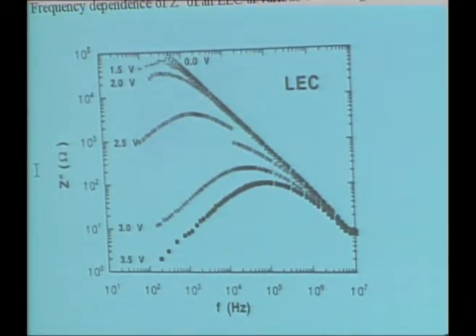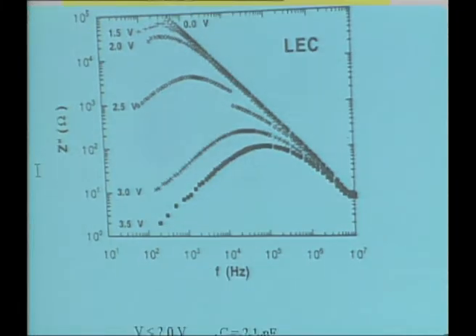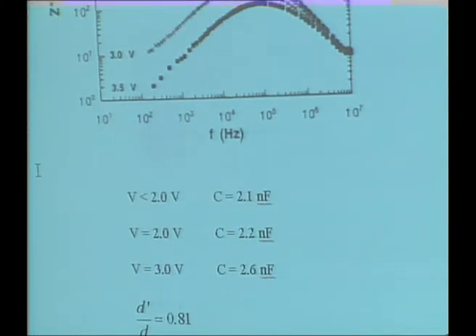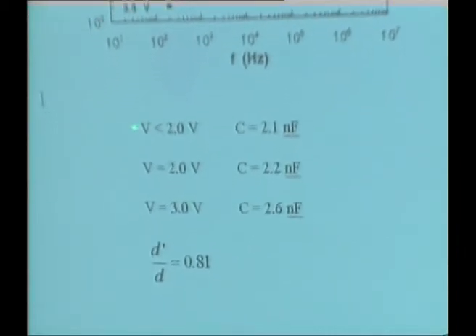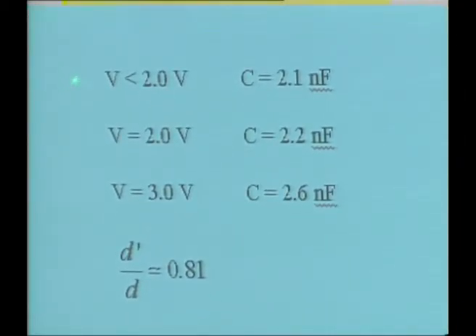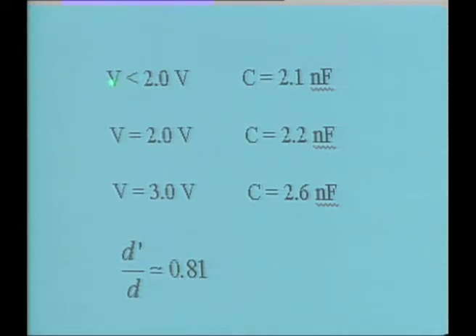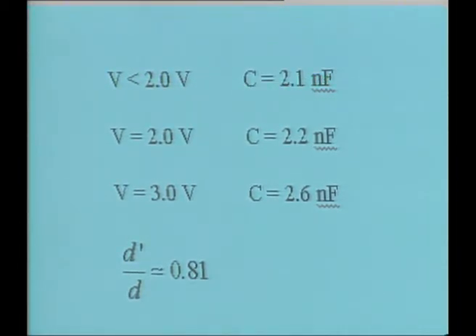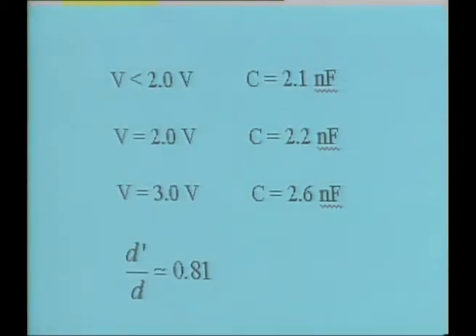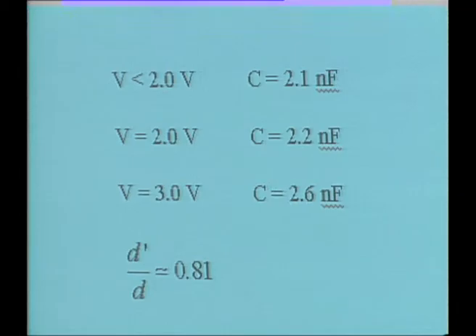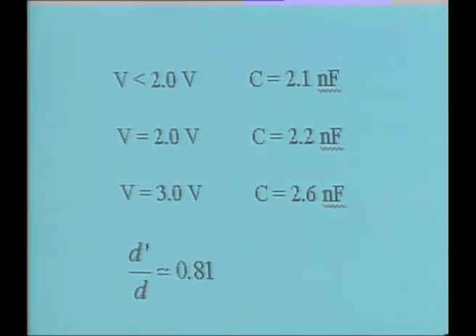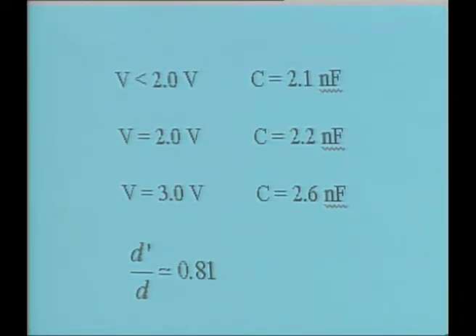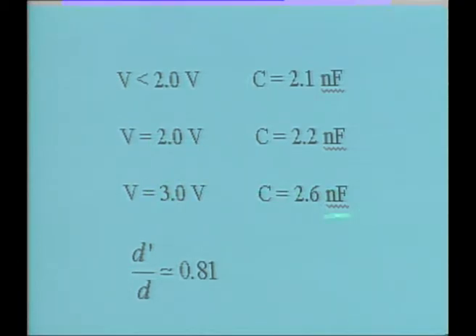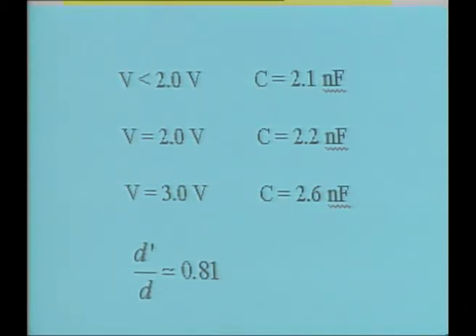It's in terms of complex impedance. This is the imaginary part of the impedance. But here are the answers. Okay, in the pristine state, at voltages below the threshold, the capacitance for this little device, whatever size it is, was about 2.1 nanofarads, epsilon A over D. Okay, when you go up to 3 volts, it turns out to be 2.6.